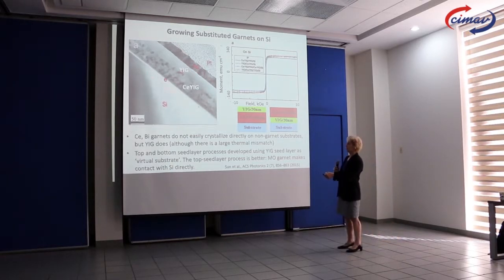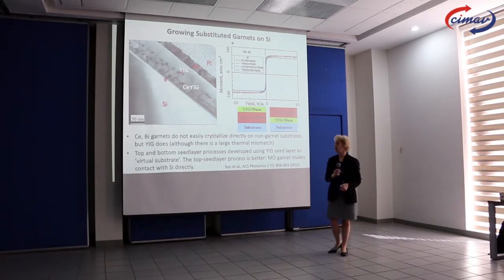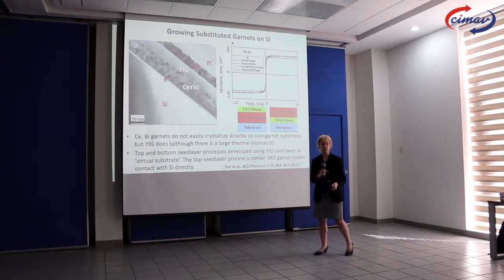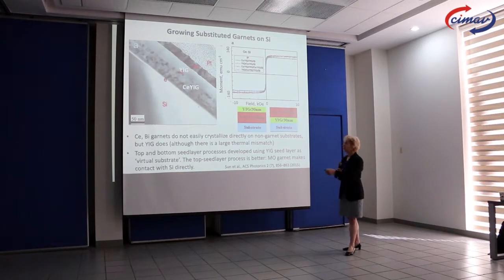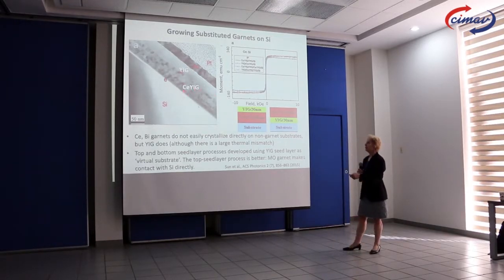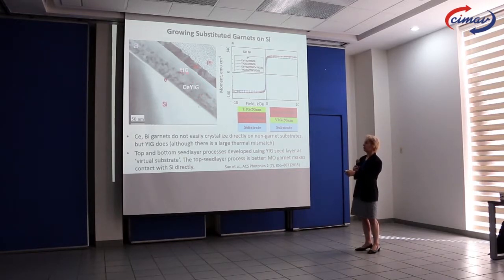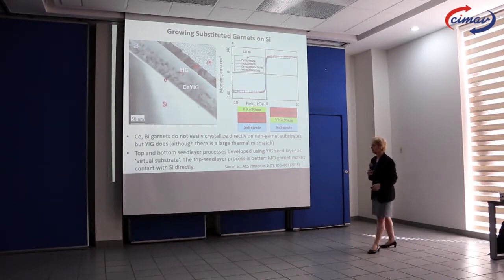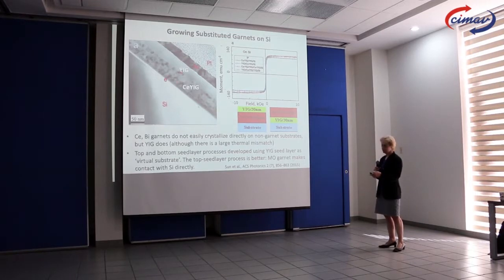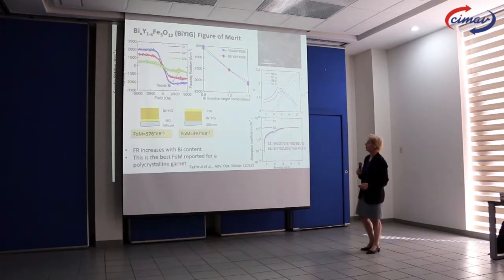So there's a silicon substrate. It turns out that for cerium YIG, if we grow it directly on silicon, it doesn't crystallize properly. But if we put a layer of YIG on top, it does. So cerium YIG is not very stable. It produces cerium oxide and yttrium oxide and iron oxide. But if you grow it next door to YIG, then it crystallizes as garnet. So we can use this process to make thin films of cerium YIG.